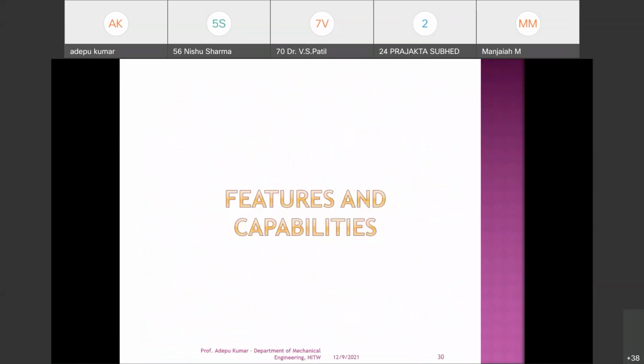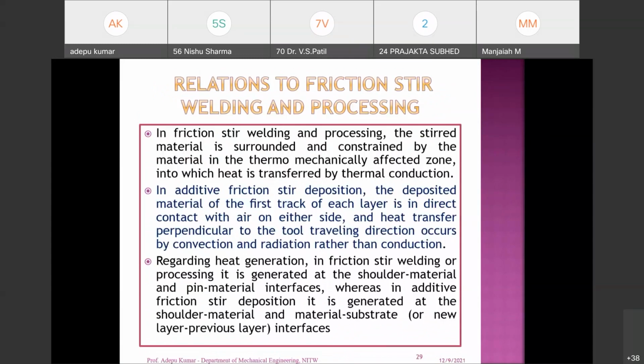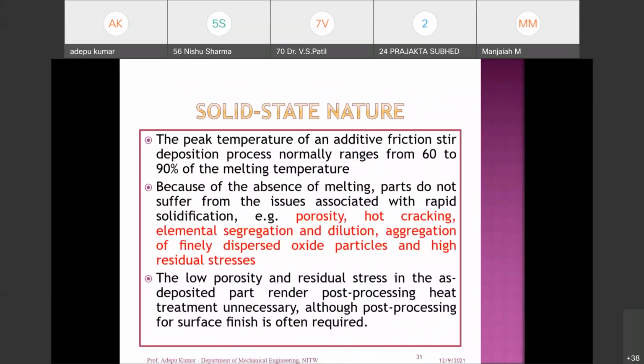Yeah, this is all the information related to what I spoke just now regarding heat generation. Due to the solid state nature, the peak temperature of an additive friction stir deposition process normally ranges from 60 to 90% of the melting temperature. Because of the absence of melting, parts do not suffer from the issues associated with rapid solidification.